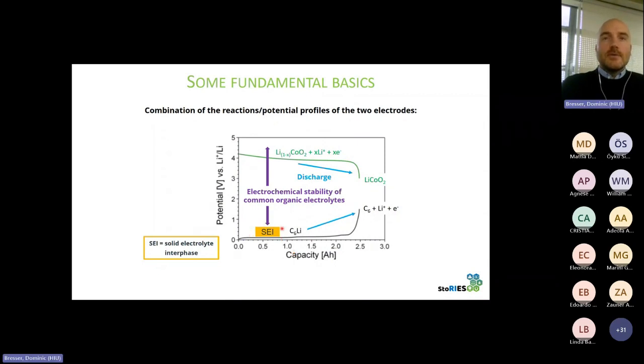Finding a solution for this, I think we've been pretty lucky that by finding EC, basically when it's reduced, it forms a stable passivation layer on top of the graphite electrode, the so-called solid electrolyte interface, that eventually enabled kinetically stabilizing this interface, and so, let's say, not requiring any more thermodynamic stability of the electrolyte towards such low potentials.